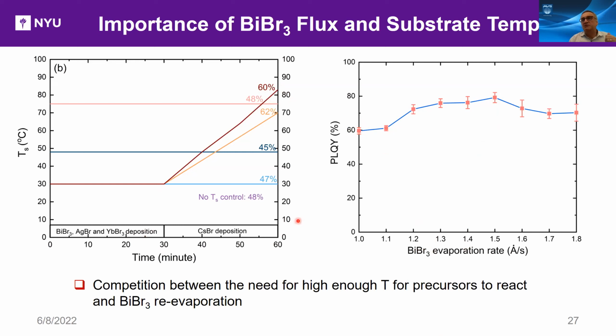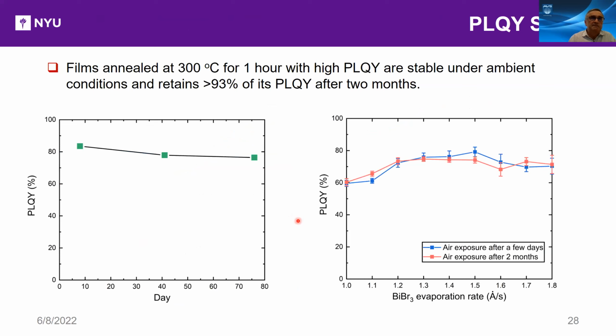When you look at the films that are deposited at low temperature, you do find the target material, the cesium, silver, bismuth bromide, but you also find still unreacted precursors. So the reaction is not complete and the annealing is needed.